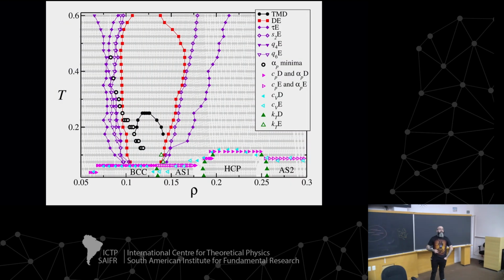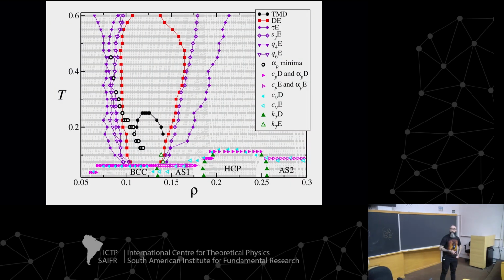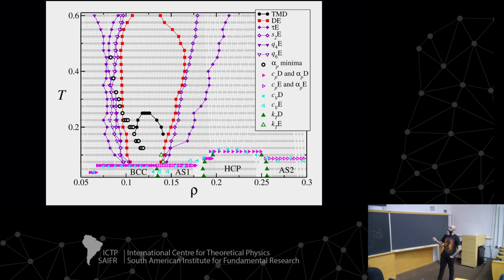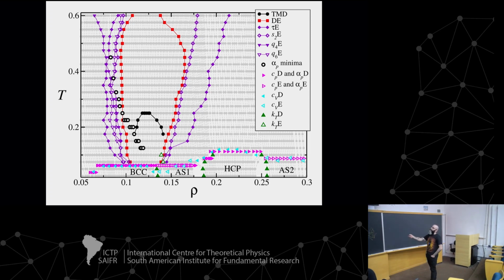And well, this is the phase diagram, the complete phase diagram. Each gray point was one independent simulation. You can see here the solid phase, the ordered and the disordered phases, all the anomalies. Here we pick up the discontinuity or the maxima in CP, CV, alpha P, and KT. You can see that it separates the phases.